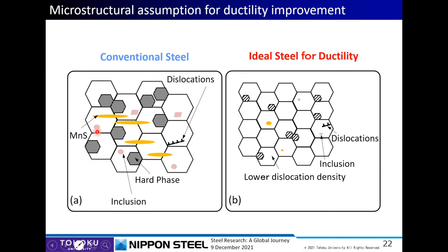We decrease the number of inclusions such as MnS or other inclusions. Also, we minimize the size of these inclusions by applying advanced technology in steel making. Also, we decrease the dislocation density in this highly ductile steel. But in order to compensate the tensile strength, we refine the microstructure so that we can get almost identical tensile strengths between conventional steels and highly ductile steels. Also, we made the second hard phase smaller to get higher elongation.